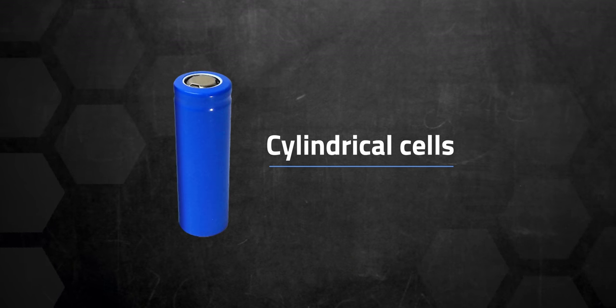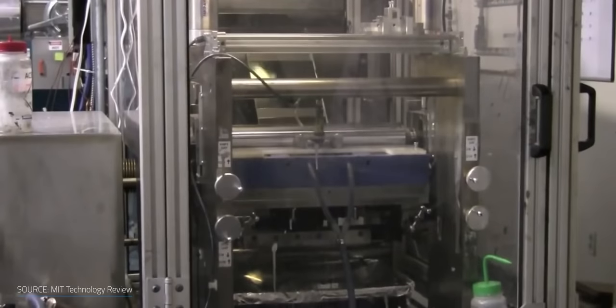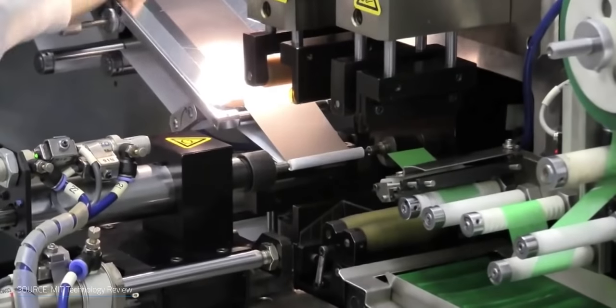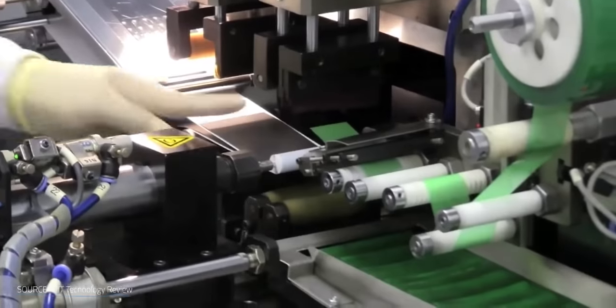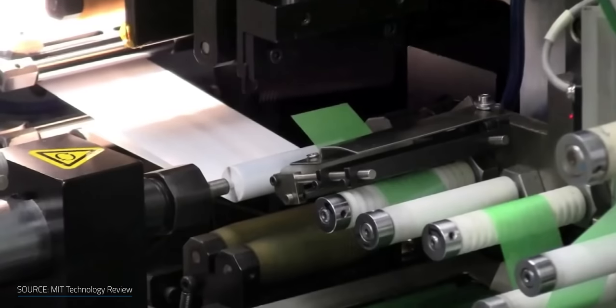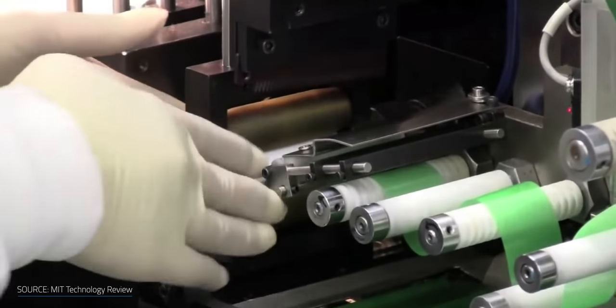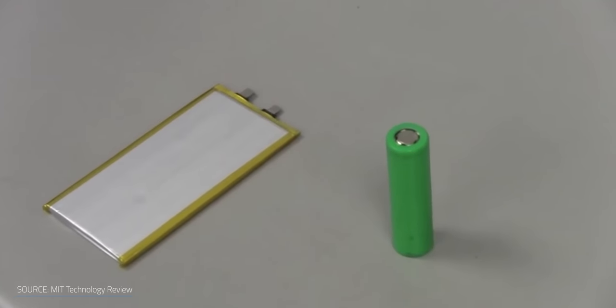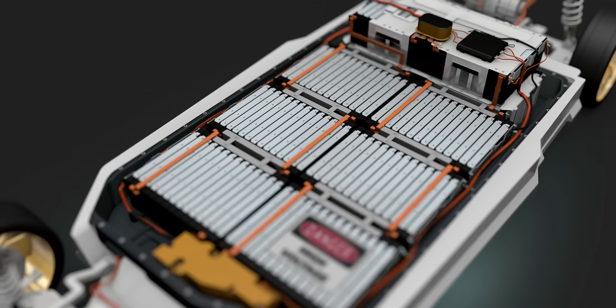There are three common forms you'll see most often when it comes to EVs, storage, and consumer electronics. Cylindrical cells have been around since the 1950s with a few good benefits: manufacturing techniques have improved significantly over the last few decades, leading to lower costs per kilowatt hour, and the cylindrical structure offers excellent stability — it can withstand high internal pressures and doesn't deform or change size. When manufacturing a cylindrical battery, the cathode, anode, and separator are spread out in thin sheets, which are then rolled up like a jelly roll. They're then cut into segments and wrapped in a metal protective case, and the shape offers extra structural stability when laid out in a battery pack.